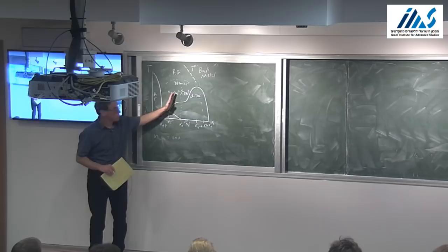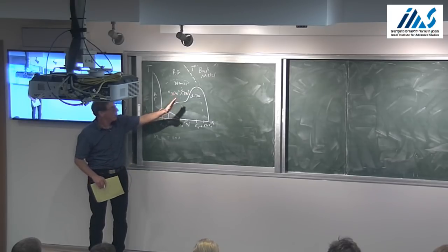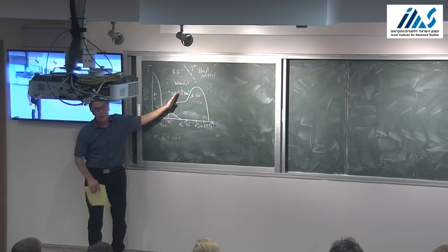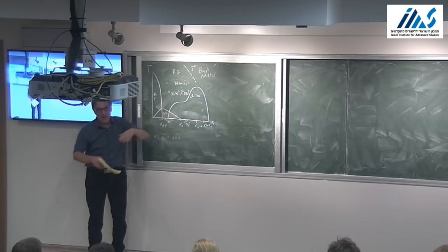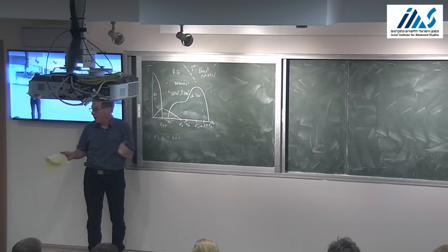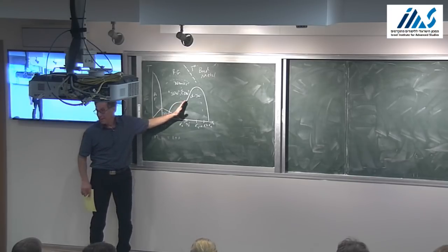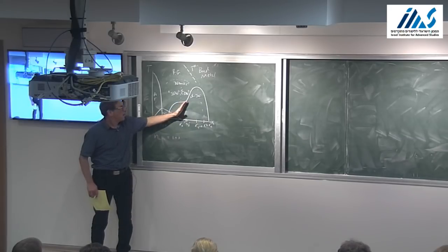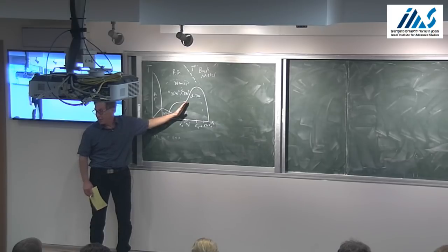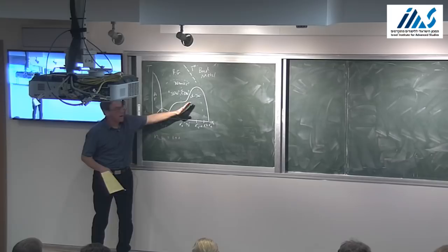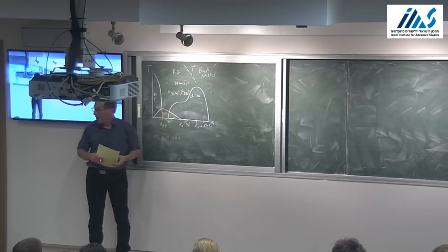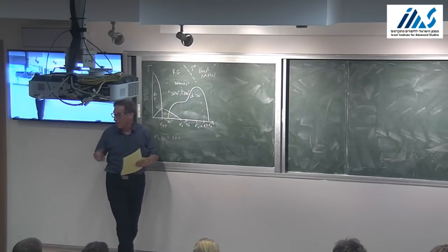But empirically, there are rather different behaviors of certain correlation functions here. Here, if you do neutron scattering, you see lots of low-energy magnetism, with some substantial correlation length for the spin correlations, large compared to 1. Here you see nothing in terms of low-energy magnetism, there's generally a substantial spin gap, and spin correlation lengths are never more than about 1 lattice constant, but you see something in the way of charge density wave correlations when you look at, say, X-ray diffraction.